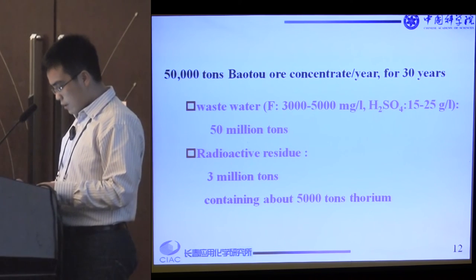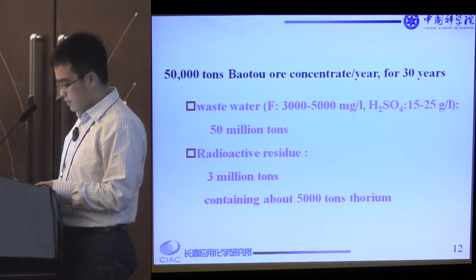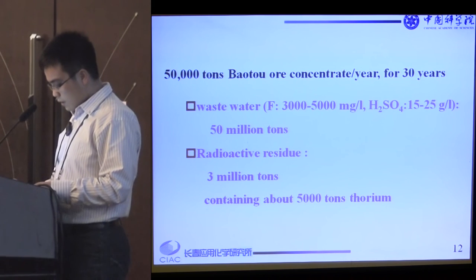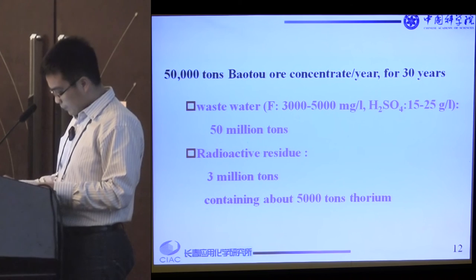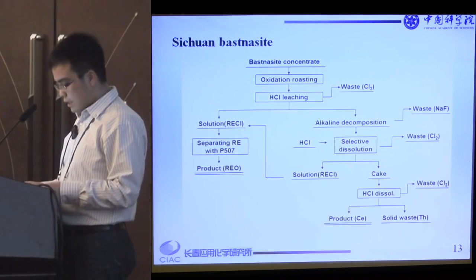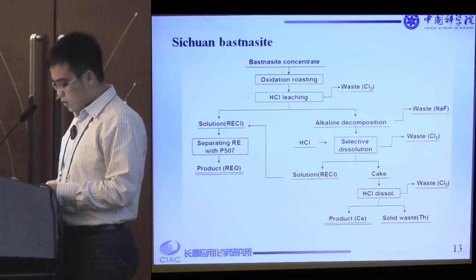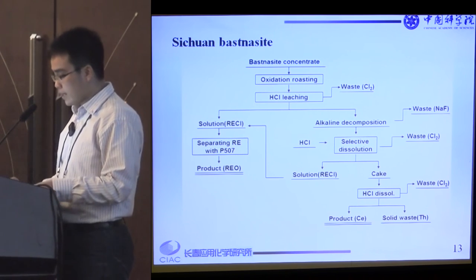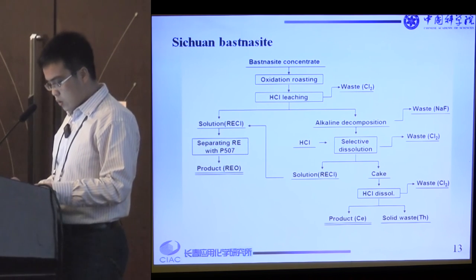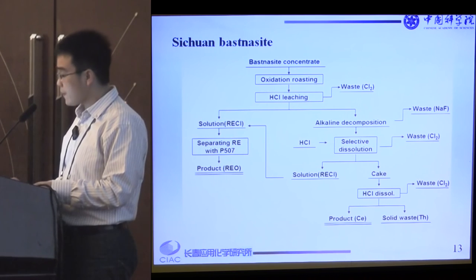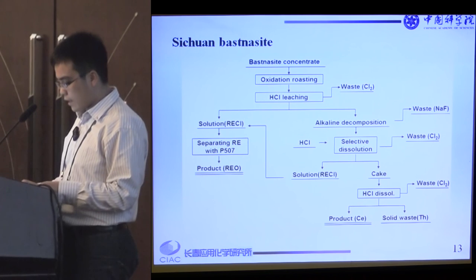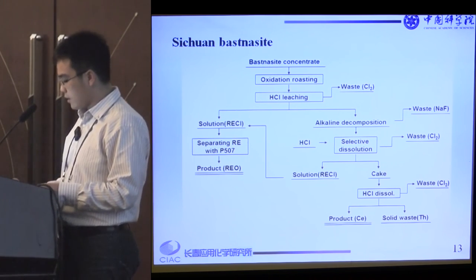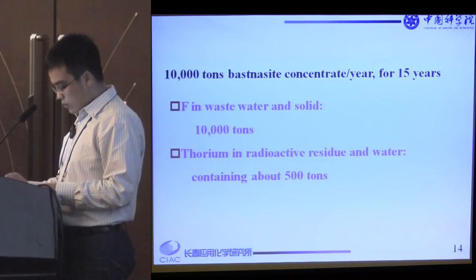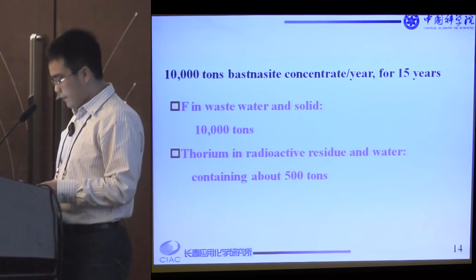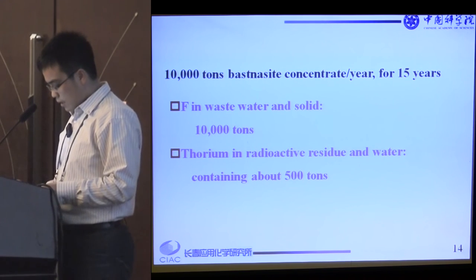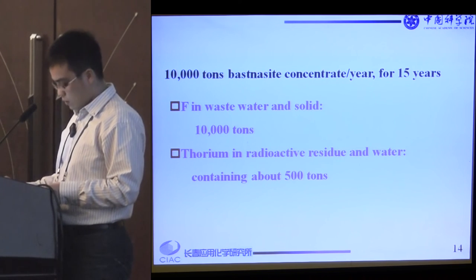To mine 50 thousand tons of Baotou ore concentrate per year for 30 years based on this method, there will be 50 million tons of waste water and 3 million tons of radioactive residue. The present metallurgical process in Sichuan shows some resemblance to that of Baotou ore. The process includes oxidation roasting, hydrochloric acid leaching, selective dissolution, and so on. The rare earths are separated by P507, and thorium is also left unrecovered in the waste residue. To mine 10,000 tons of Sichuan ore concentrate per year for 15 years based on this method, there will be 10,000 tons of waste water and 500 tons of radioactive residue.